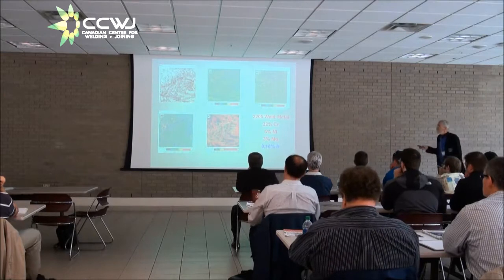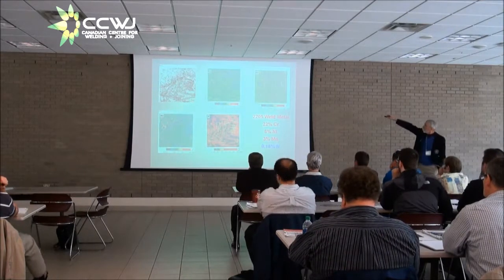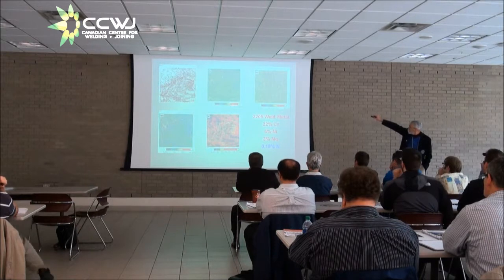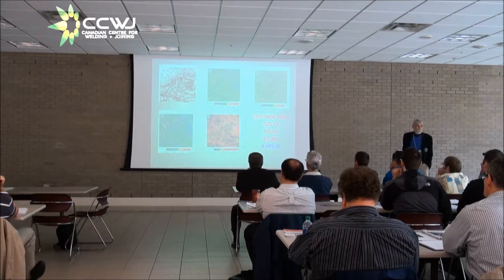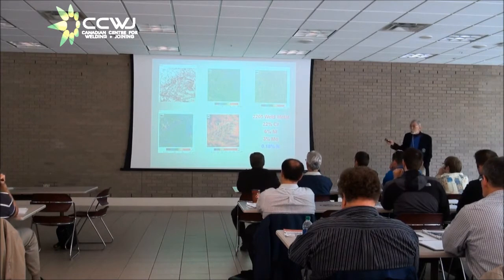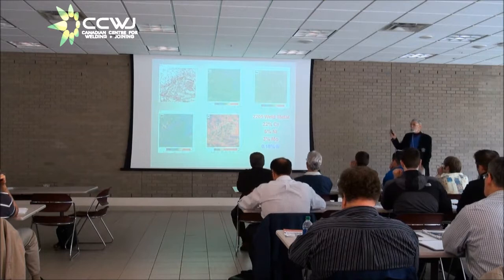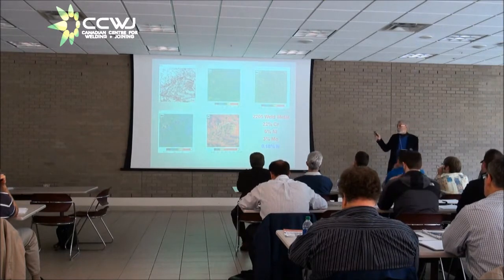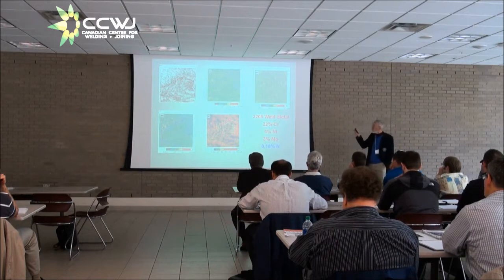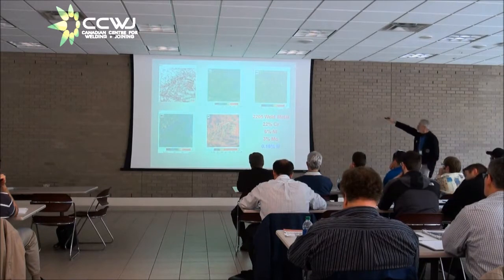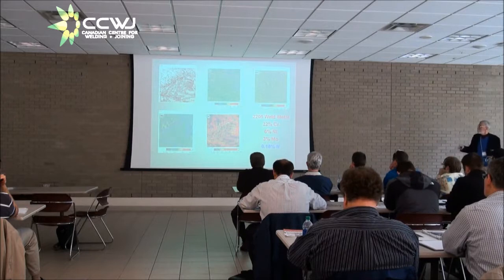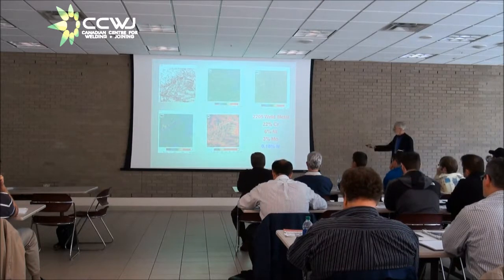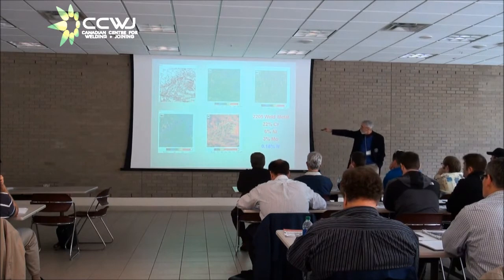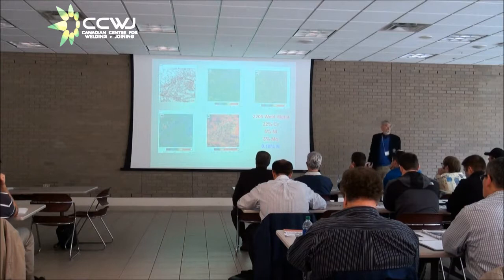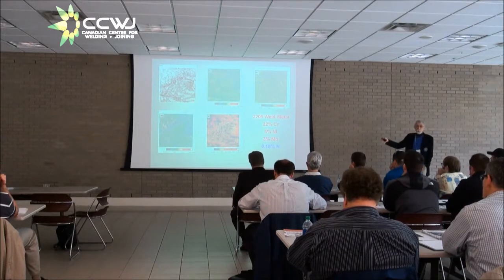Now, when you look at the alloy element mapping, you can see a little bit of the chromium partitioning. If you've got really good imagination, I think you can see there's a tendency for a blue outline here. That's a ferrite grain boundary which is completely covered with austenite. This tells you that the first formation of austenite took place at a higher temperature, where chromium had a chance to diffuse out of the austenite. And if you look at the nickel map, you still can't see anything but the little hexagonal shapes. Nickel is the slowest diffusing of all the elements. If you look at the molybdenum map, you can see it better now, that blue outline of the big ferrite grain, where the molybdenum is bailing out of the areas that transform to austenite.